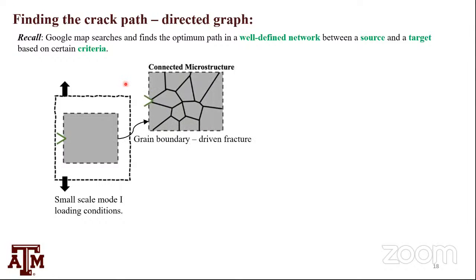So let's focus on one simple microstructure, a case of intergranular fracture, grain boundary driven intergranular fracture, when I have a connected microstructure. Do I have a source? Yes. We're doing a mode 1, so I got a crack tip, I know my source. Do I have a well-defined network? Yes. I'm saying that my crack will always follow grain boundaries, and I'm just focusing on 2D, so I got a nice well-defined network. Do I have a target? No. I don't know where I'm going. Crack doesn't know a priori what's going to end up on the right side. Do I have a criteria? Well, we don't know yet.